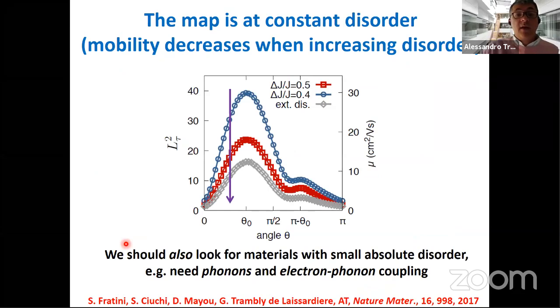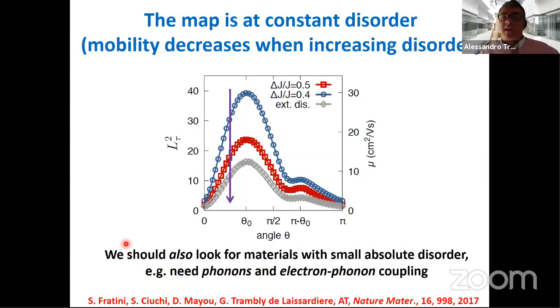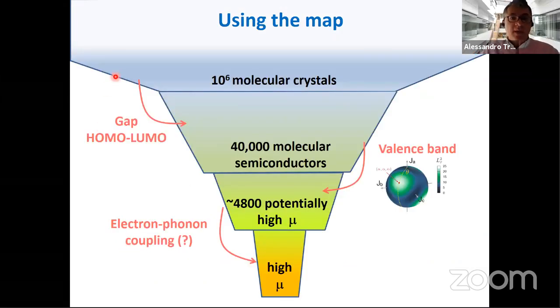So the last step is that if we want to predict properties, it's not enough to just look at the relative sign or relative size of the coupling. We also need to compute the electron phonon coupling because, of course, the disorder, whether it's large or small, will affect the coupling. So the last step we have to do, after reducing the total set of molecules from 1 million to 40,000, and after using the map to identify the best 5,000 potentially high mobility materials, is to compute the electron phonon coupling.